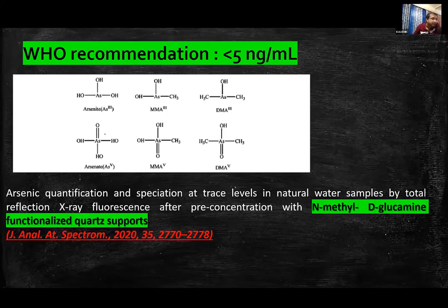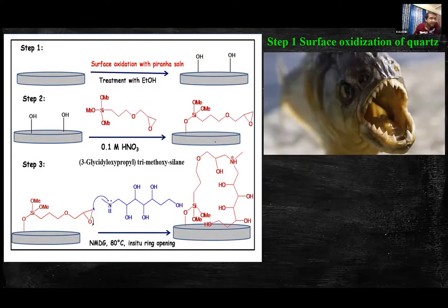Now, among these two inorganic forms of arsenic, arsenic 3 is the most toxic one. In this work, I have developed a novel adsorbent called N-methyl D-glucamine, and I have functionalized this adsorbent on the quartz sample support. I have used this novel adsorbent for the speciation of arsenic in different types of water samples. These are the different steps carried out during the immobilization of the NMDG membrane on the quartz sample support. This NMDG is the extractant which actually absorbs the arsenic.